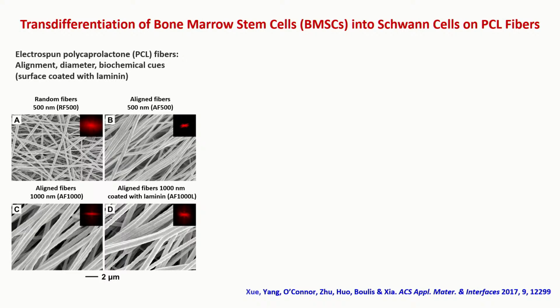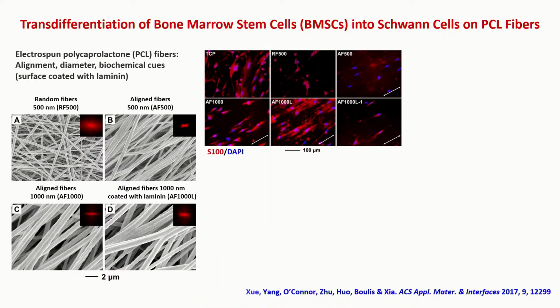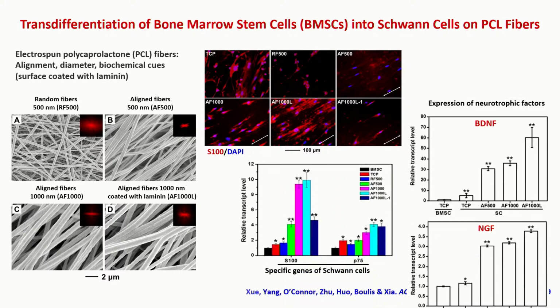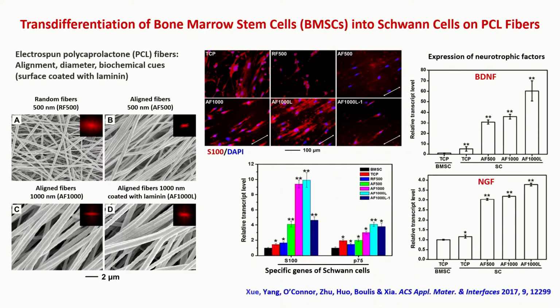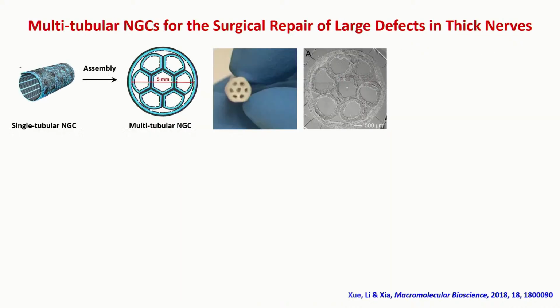It's almost there. In this case, we looked at how we can control the differentiation of bone marrow stem cells. We looked at different conditions. The result is that under the right conditions, like the diameter of the fibers and the surface composition, for example, if you put laminin on the surface, you do observe very significant differentiation of these bone marrow stem cells into Schwann cells. So that's very promising. And finally, we developed a new design for the conduit.